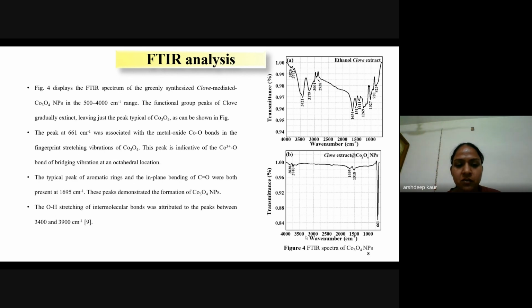The typical peak of aromatic rings and in-plane bending of C=O were both present at 1695 centimeters. These peaks demonstrate the formation of Co3O4 nanoparticles. In the region of 3400 to 3900 centimeters, the OH stretching of intermolecular bonds were attributed.